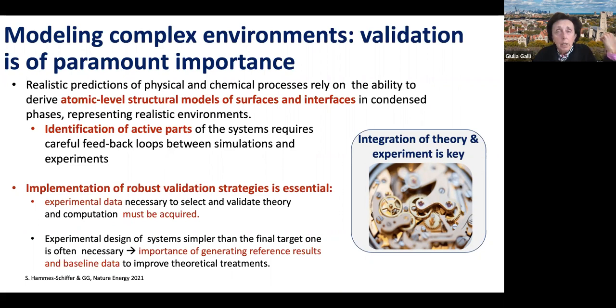And this is why our collaboration on bismuth vanadate was successful, because the experimentalists were willing to go back to the lab and make measurements on single crystals, which is what we can simulate, and tell us, okay, this level of theory is decent and we can use it for trends. If you only have, for example, thin or disordered films that eventually are what ends up in the device, I understand that you will not be able to do a proper validation. And I cannot emphasize enough the importance of generating reference results and baseline data that we need to improve our theoretical treatment.